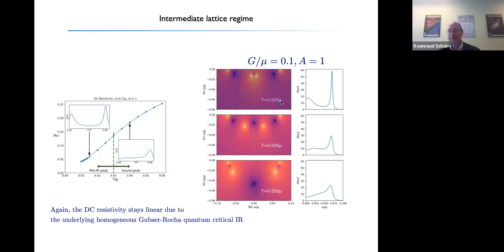And you can now study the system again as you increase the temperature. And as you increase the temperature, we've just seen that these poles start moving. You now no longer can completely explain the movement in terms of hydrodynamics, because Umklapp hydrodynamics doesn't work, but you can simply trace what happens as you increase the temperature. And what you see is that these two poles of the mid-IR part start moving off further and further away until they basically, well, they don't really collide with the sound peak, but they get shielded from the real axis by the sound peak. And in terms of the optical conductivity, it does look like this peak gets eaten by the sound mode. And you have a very amorphous, bad metal-like signature in the optical conductivity.